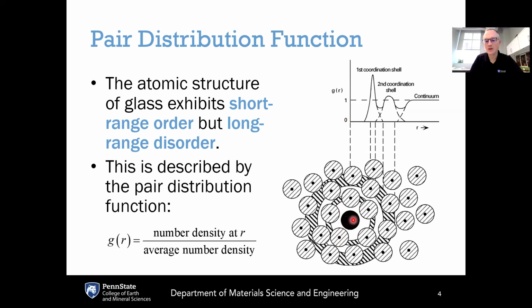Now, as we increase r, we are expanding the shell out a little at a time, and you'll see that the pair distribution function remains at 0 over some distance here. And this remains at 0 because of the repulsive nature of atoms. If they are too close to each other and their electron shells are overlapping with each other, again, because of Pauli's exclusion principle, that is going to be highly unfavorable from an energetic perspective. And therefore, the probability of finding another atom that is strongly overlapping with the central atom is going to be pretty close to 0. So this pair distribution function remains at 0 until we get to the first nearest neighbor.